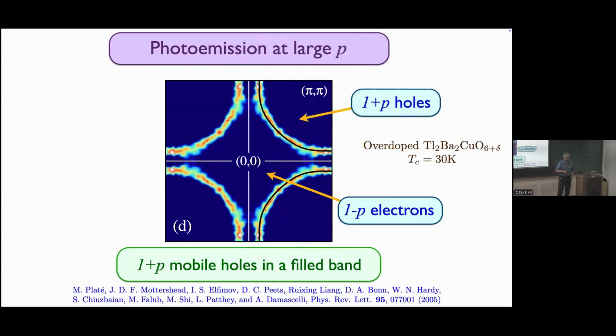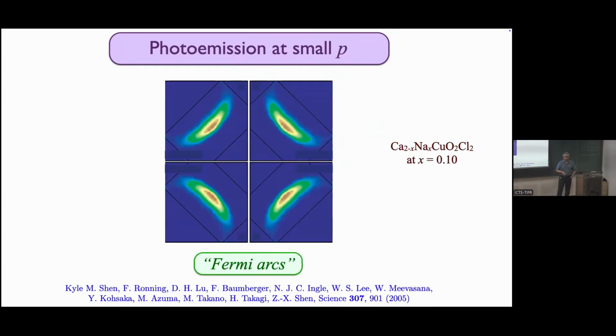Okay. But when you lower the doping and you lower the value of P, then this beautiful Fermi surface seems to get truncated into what are called Fermi arcs. So what are these arcs? I'm going to present a theory of that, but this is what they're called, and it's quite a striking feature because in nobody's theory, which is self-consistent, do you ever get Fermi arcs. You can get pockets with low intensity at the back, and if so, are there pockets, and what is the low intensity due to?